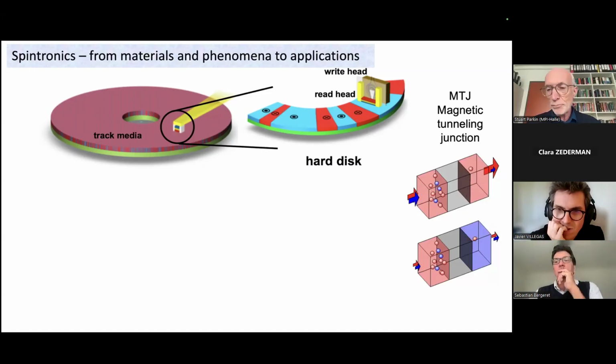And when the magnetic layers are parallel, these spin polarized electrons can find empty states of the same spin polarization into which they can tunnel, and the tunneling current is high if the two magnetic electrodes are identical. And when you switch the magnetic electrode from the red to the blue direction, then the current can be reduced. And these differences in conductance can be several 100% at room temperature.